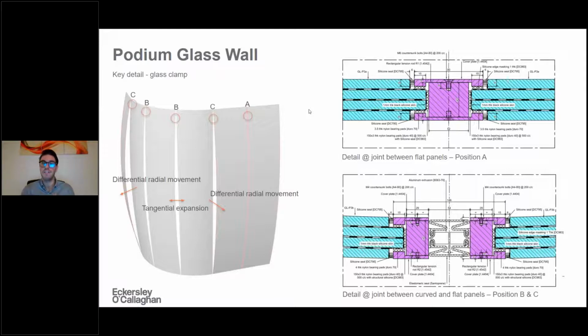challenge was to define different interfaces in terms of rods and glass connection. For position A, the typical one between flat panels, we designed a single rod which clamps the two panels, and therefore, when the panel deflects, the rod is followed by the two panels. What's happening in positions B and C, because of this differential radial or tangential movement, is that we developed a system with two rods, which are then only connected by a movement joint. Therefore, they are free to move differentially, outwards and tangentially. And therefore the two panels connected and clamped to the double rods can experience the differential movement that they will naturally have under wind load.